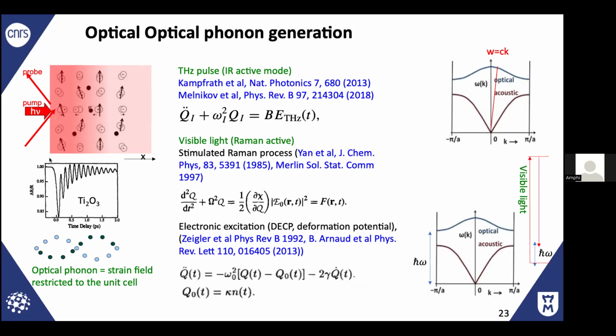If you have above band gap excitation, then you create an electron-hole pair. In that case, there is what people call displacive excitation of coherent phonons, or it's related to the deformation potential. You can generate optical phonons as well. So depending on the situation of the excitation, below or above band gap, you can generate different optical phonons. Basically, in the first case, it's infrared active phonons. And in the second case, usually you have A_g, most of the time the symmetric Raman active mode. But you can also have an E_g mode. But I will not detail this too much.